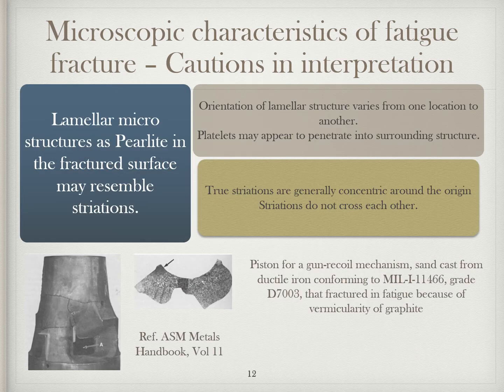Another precaution one has to take in dealing with microscopic characteristics of fatigue fracture is the caution in interpretation. The lamellar microstructures such as pearlite in the fractured surface may resemble striations. However, one clear difference is there. The orientation of lamellar structure varies from one location to another, whereas platelets may appear to penetrate into surrounding structure. The true striations are generally concentric around the origin and the striations do not cross each other.